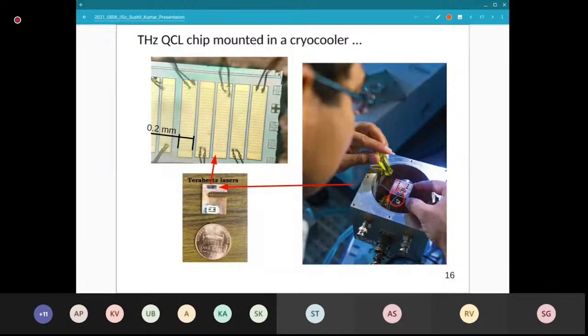This is a copper block that gets cooled to that temperature. Obviously, we then have to mount this laser mount. This is again a copper chip, the size of a coin. The actual laser chip is this. It's about 1 millimeter by 2 to 3 millimeters. If you zoom in on this chip, these are the laser cavities. Each of them is an individual laser that can potentially emit up to a watt of power. And these are wire bonds. We wire bond these, and you can see some gold wire bonds here, and using some coaxial cables, we then bias this device. That's how we electrically bias in the vacuum.